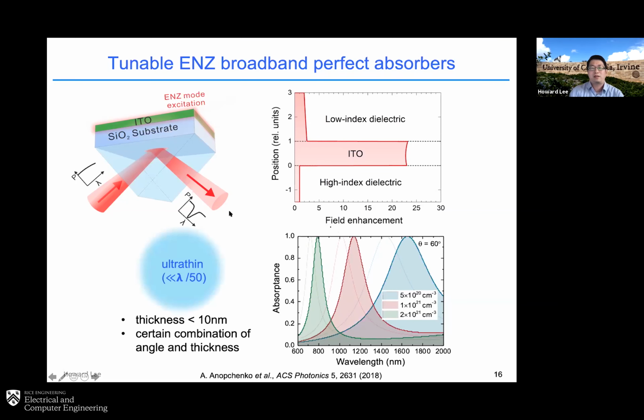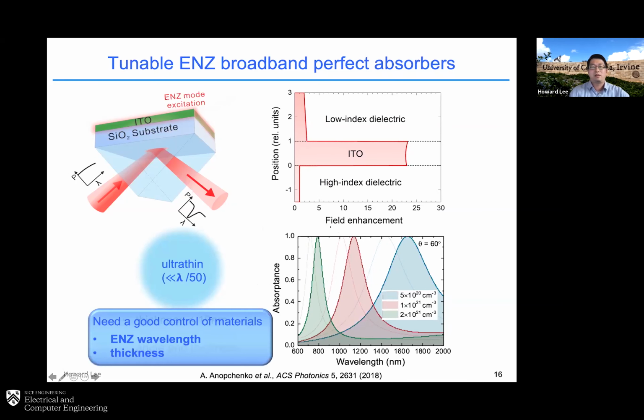And just keep in mind, to excite the ENZ mode, you actually can use a really ultra thin film. We are talking about maybe lambda divided by 50. That means in the visible range, maybe we're talking about thickness less than 10 nanometer, which is really ultra thin to make that kind of strong absorption or strong enhancement of the field. But at the same time, you need a certain combination of angle and thickness to really efficiently couple to this ENZ mode here. So what that means, if you want to really excite this ENZ mode, you need to have really good control on the material in terms of the ENZ wavelength and the thickness here.